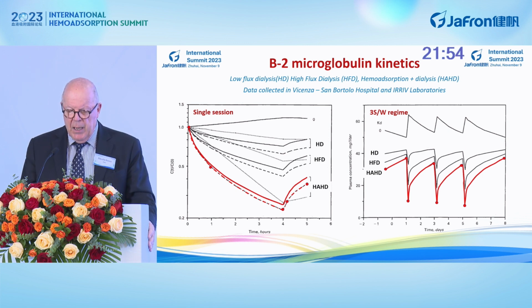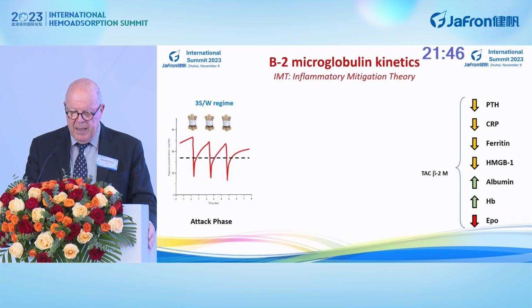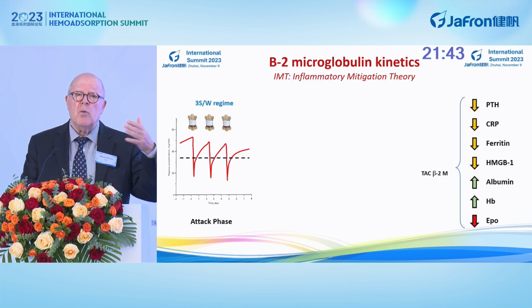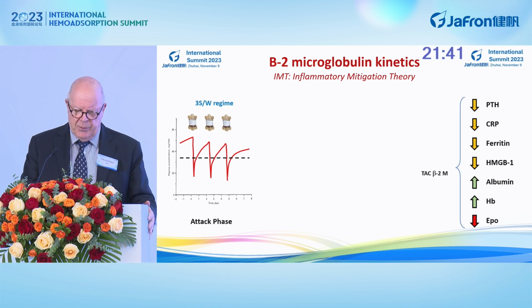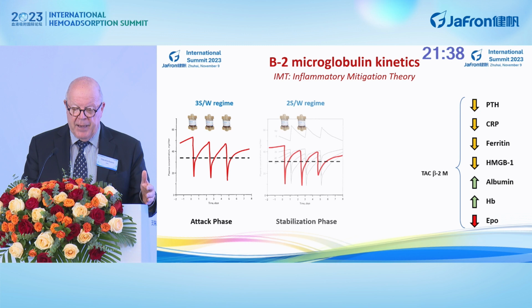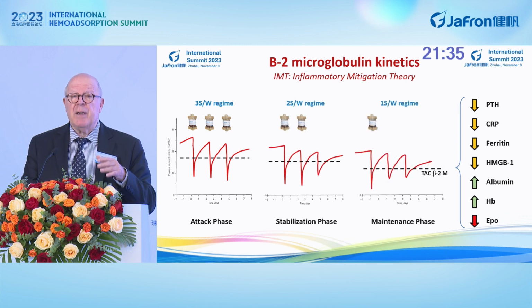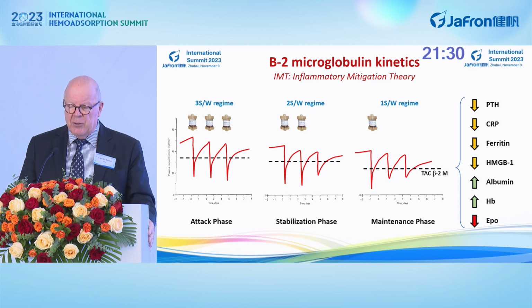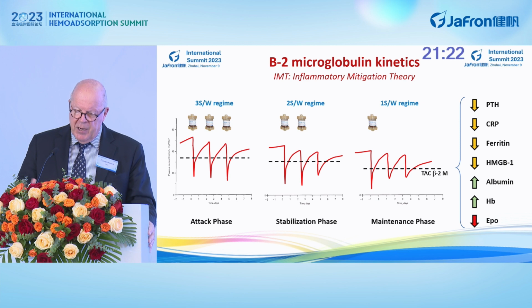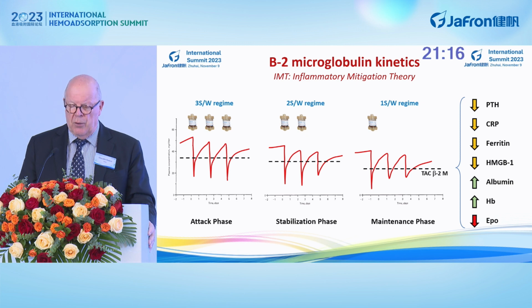And so you see, when you use, for example, a 3 sessions per week regime, that you lower the concentration of beta-2 microglobulin. But what is interesting is that when you move to subsequent sessions and you have, after the attack phase, 2 sessions per week and even 1 session per week, the time average concentration of beta-2 microglobulin decreases and remains low, including also PTH, CRP, ferritin, HMGB1, with increase in albumin, hemoglobin, and reduced need of erythropoietin.